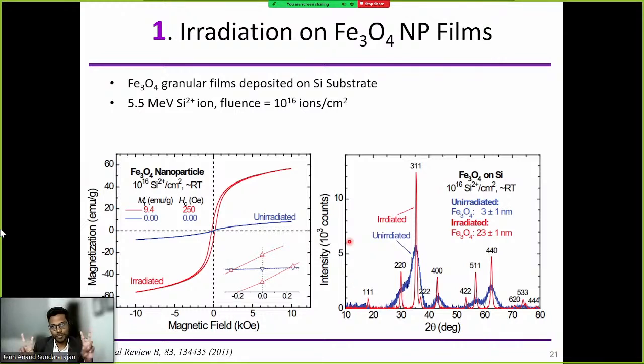So like I mentioned, we are studying two types of particles for nuclear energy applications. One is fully oxidized nanoparticle films, and that's what I'm showing here. Iron oxide, Fe3O4. These are granular films, and they are exposed to a heavy dose of silicon ions, like 10 to the power 16 ions per centimeter square. So heavy ion irradiation. The blue hysteresis loop here shows that they are unirradiated. After the radiation, this is how it looks. So what has happened? Before irradiation, it was basically paramagnetic, right? And after irradiation, it became ferromagnetic. Basically, it started to gain some magnetic property. So there is a huge change happening for the iron oxide material.